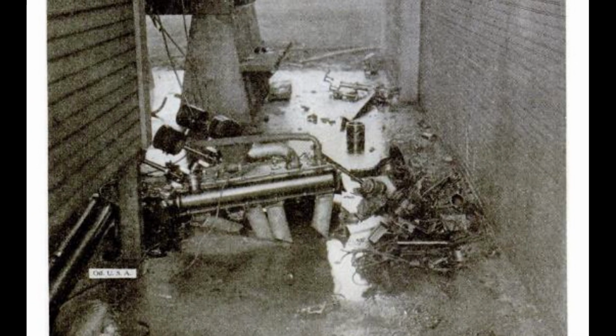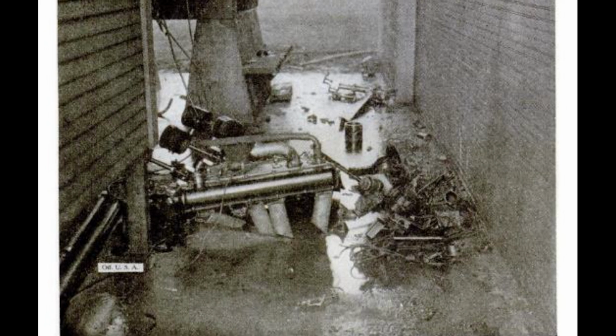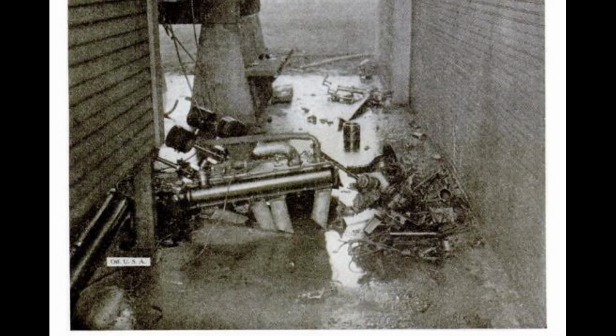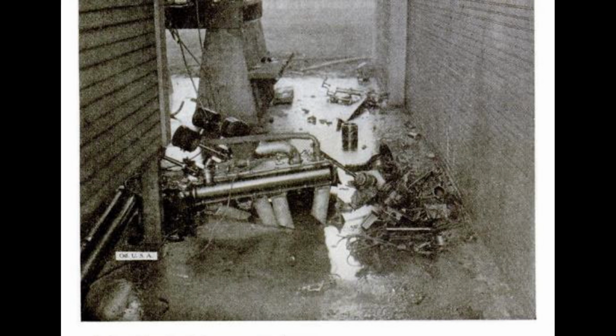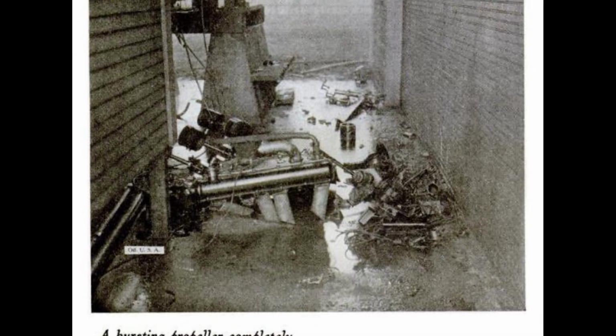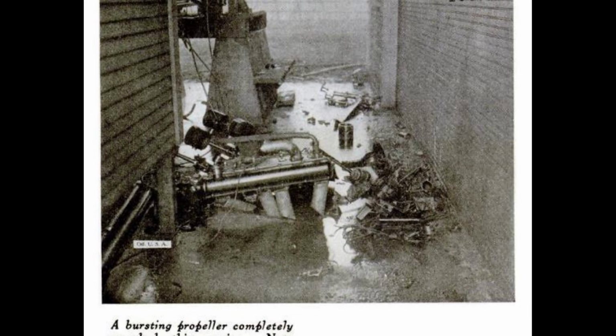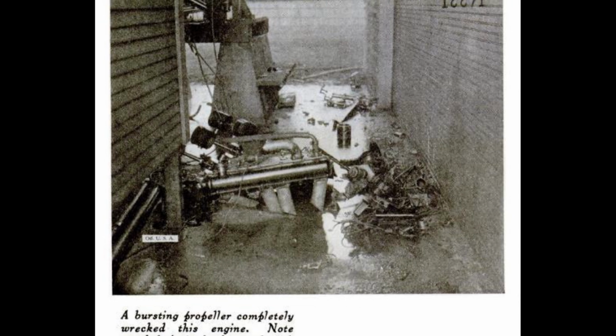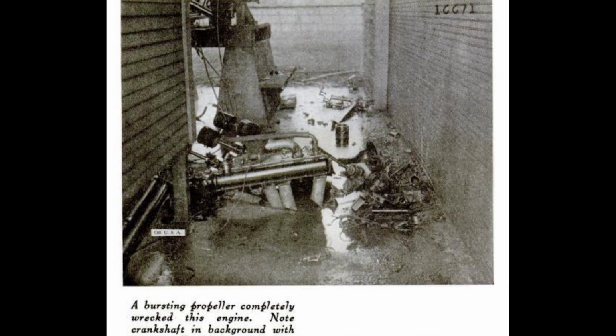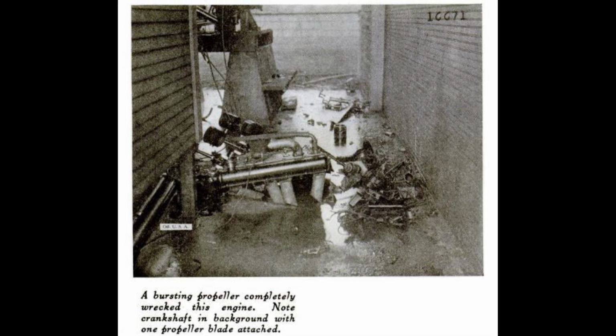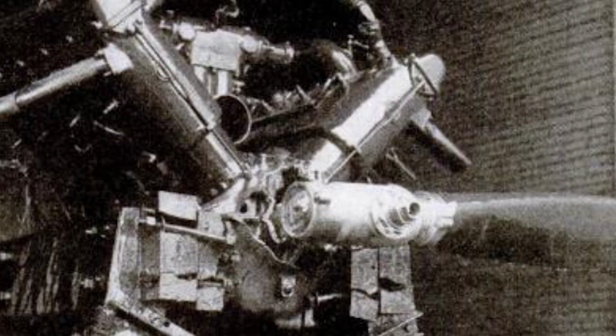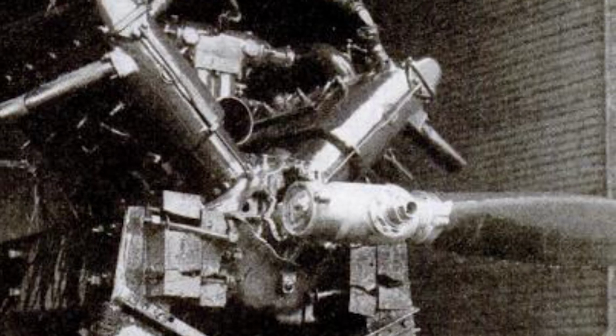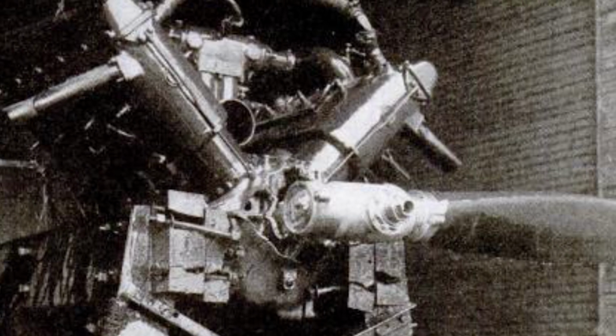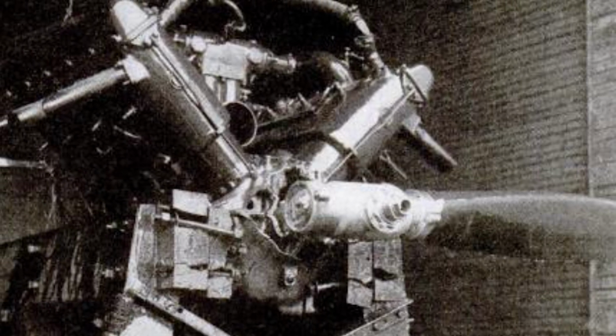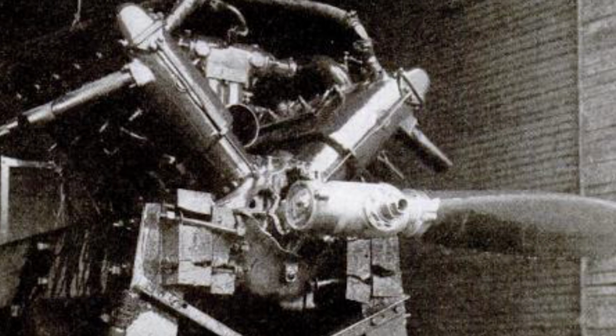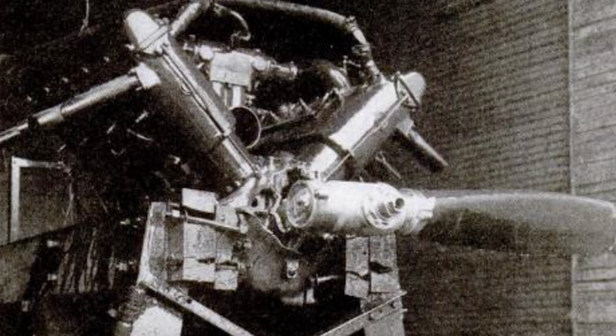Centrifugal force causes each blade to pull outward with a force of more than 20 tons when the engine is at full speed, although the blade itself only weighs about 30 pounds. This does not cause vibration because each blade pulls against the other, and in manufacture, both blades are made exactly the same weight, tested by balancing the propeller on knife edges so delicate that the weight of a fly would be indicated. Since any difference of weight between the two blades is multiplied by more than 1,000 times by centrifugal force, such slight lack of balance as results from the application of an extra coat of varnish to one blade will produce an unpleasant vibration.